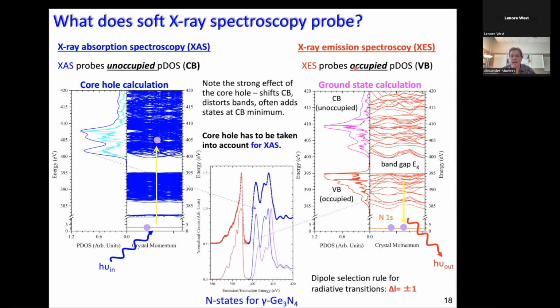Then you put this together, so you always see here the projected density of states, and this is now for 1K, calculated and measured for gamma germanium nitride. You see here the calculations, emission and absorption, and here you see on top the measured spectra.